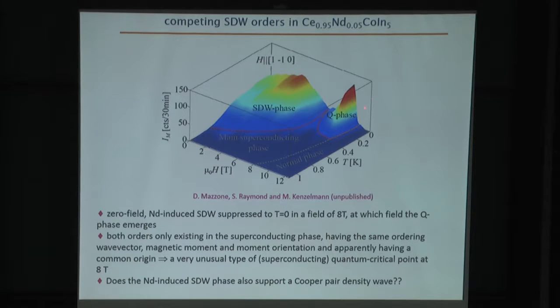So I've mentioned that this Q phase that's found in pure cerium cobalt indium-5 hosts a Cooper pair density wave. I think it will be very interesting for future experiments to see if this neodymium-induced zero-field spin density wave state also hosts a Cooper pair density wave, in which case this quantum critical point here must be extremely unusual.